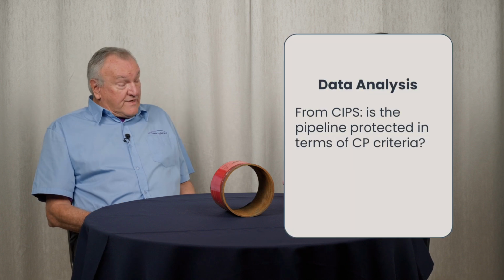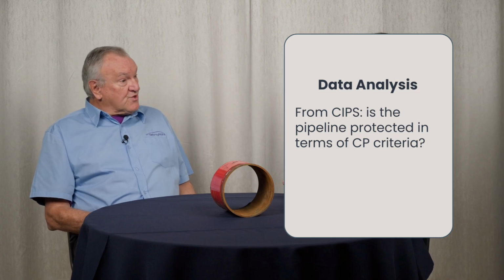So you take the defect indications and then you take the CIPS data and you say, well, is the pipeline protected in terms of cathodic protection criteria? So we've spoken previously about measuring potentials. And is the pipeline more negative than minus 850 millivolts with respect to copper sulfate half cells or not? At the same time, with the CIPS survey, you can switch the rectifiers or cycle the rectifiers is a better word to use to get what we call on and off data. And it is the off data that is more critical in terms of whether or not the system is protected.